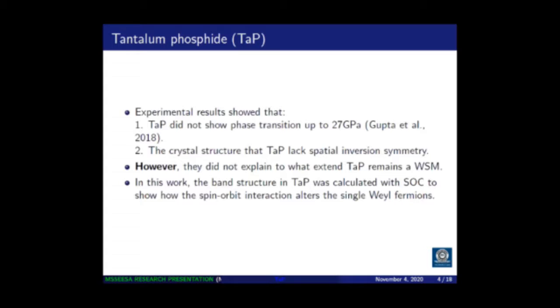Now, the experimental result has shown that TaP did not show phase transition up to about 27 gigapascals. It was done by Gupta and his team. Also, the crystal structure for tantalum phosphide lacks spatial inversion symmetry. However, they did not explain to what extent TaP remains a Weyl semimetal. Therefore in this work, the band structure in TaP was calculated with the spin orbit coupling to show how the spin orbit interaction alters the single Weyl fermions.